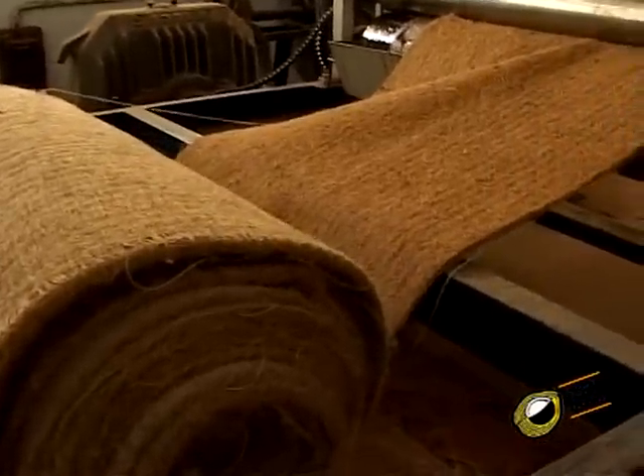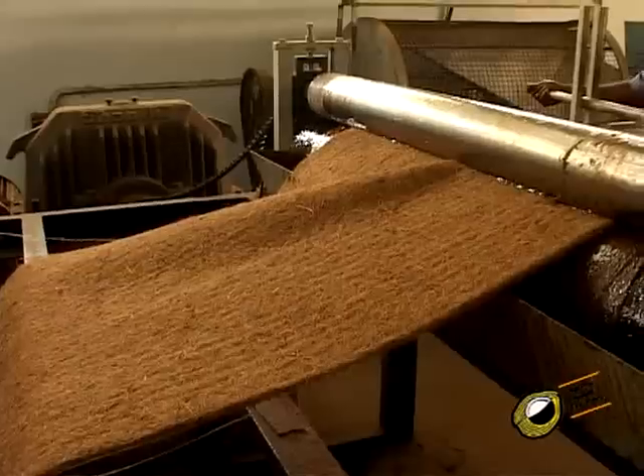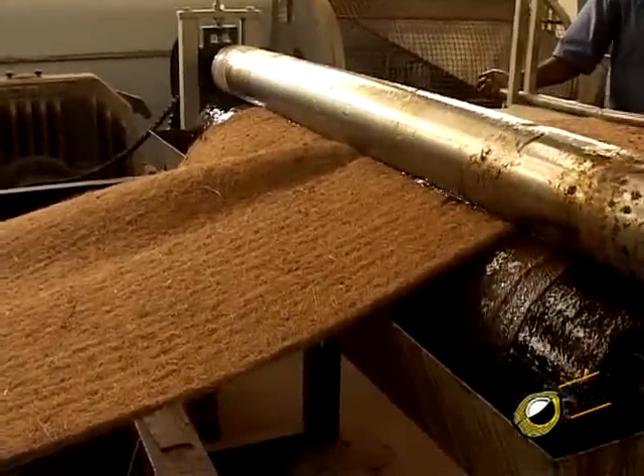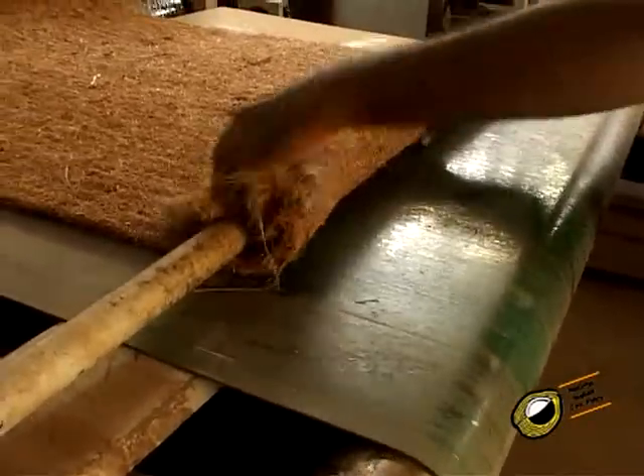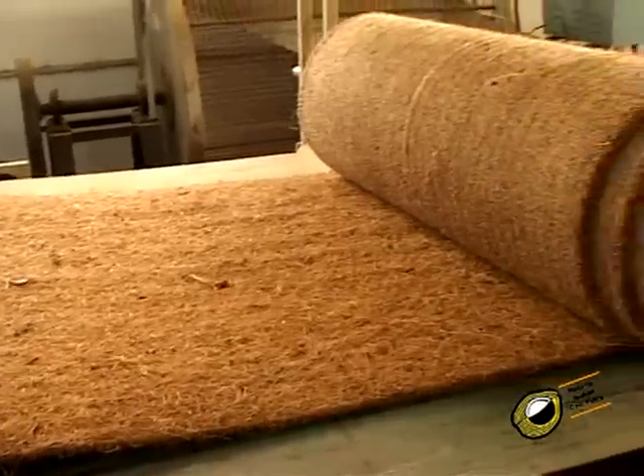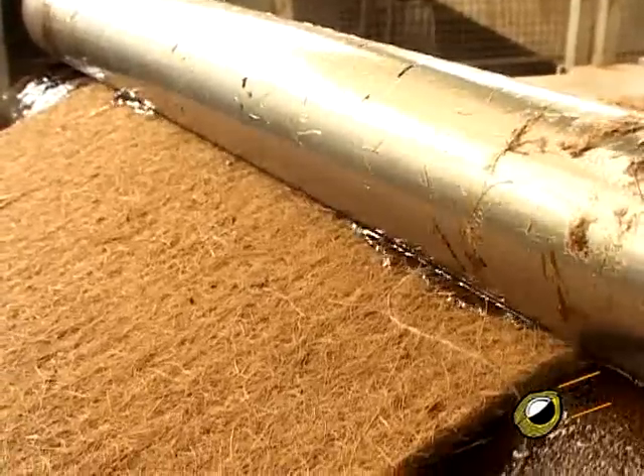After that, the cut material is fed to the phenol formaldehyde coating plant roller. The resin is transferred to the needle felt with the help of a spreader having a set of squeeze rollers in the fabric carrier of resin. Any excess resin coated onto the felt is removed by passage through a set of squeeze rollers.